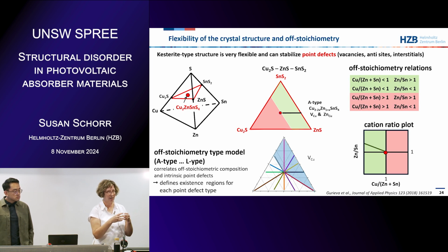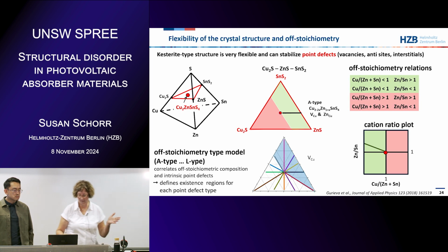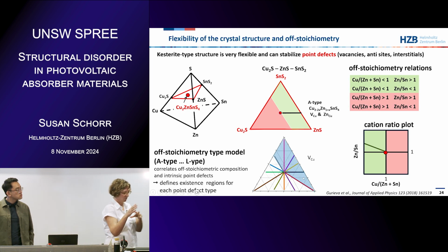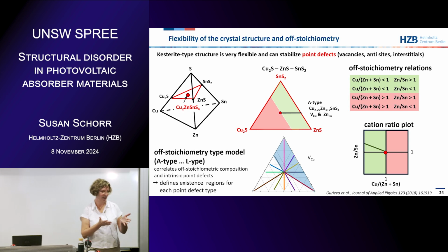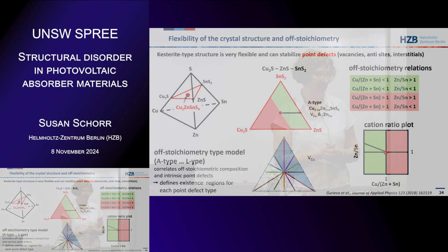Even if you say, okay, my composition is not so inhomogeneous, these are dangerous points when you cross the lines. If you are between two lines, then your composition can vary a little bit, but you will have the same defect types. But if you cross the line, your composition will vary a bit, but you have different defect types. So maybe this then happens just by chance.